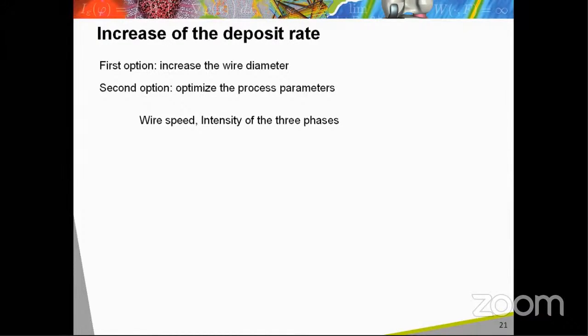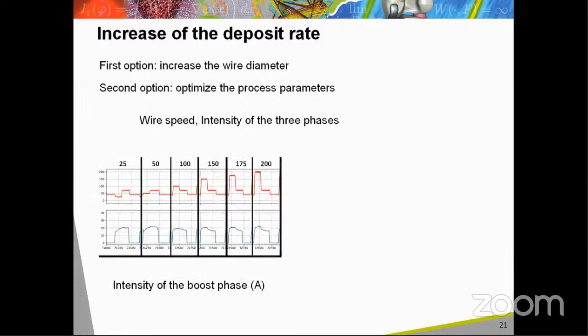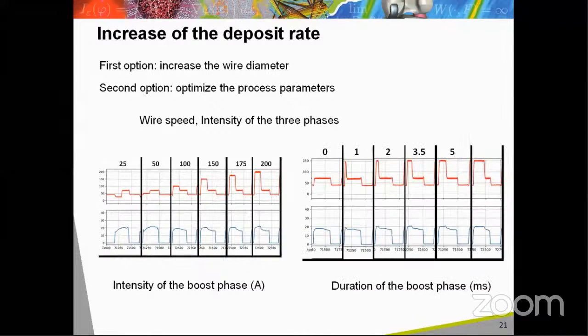The deposit rate depends on many factors, such as the wire feed rate, the current of the various phases of the transfer cycle, or the duration of these phases. However, two factors were identified to have the greatest influence: the intensity and the duration of the boost phase. The value of the boost phase current can be changed between about 20 and 300 amperes, and the duration of the boost phase can be changed between 0 and about 10 milliseconds.